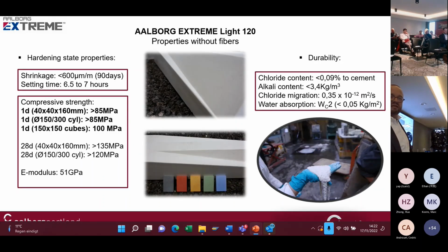And then in hardened state, okay, we can say that compressive strengths at 1 day are above 85 MPa and at 28 days, depending on the kind of samples, above 120 or 135 MPa. And then durability wise, we see that also chloride migration and water absorption is very limited.